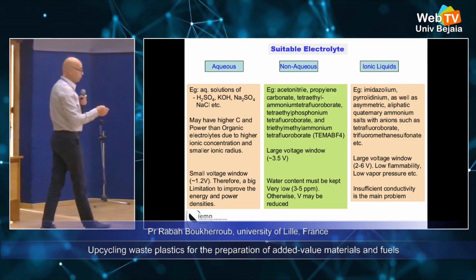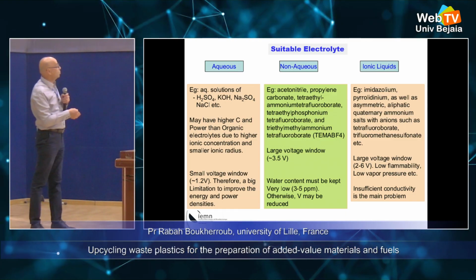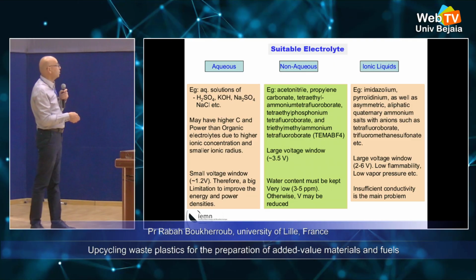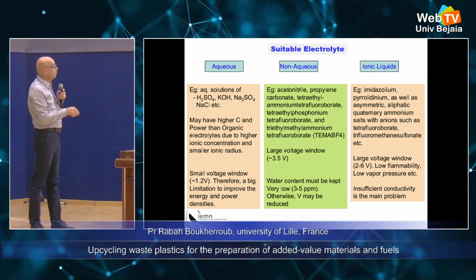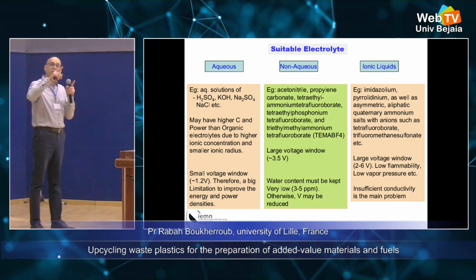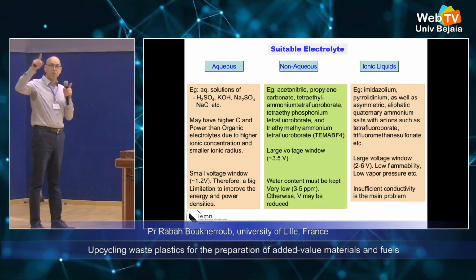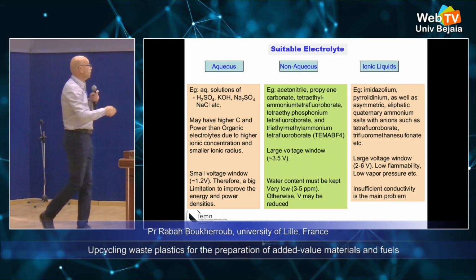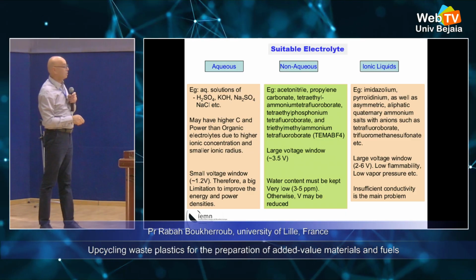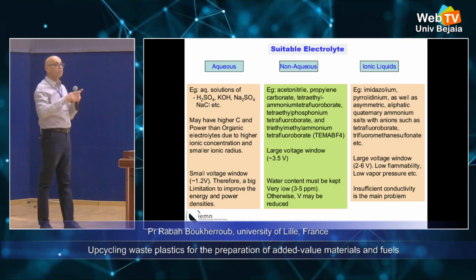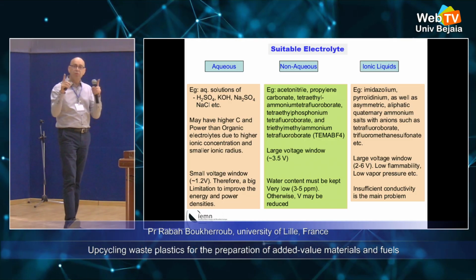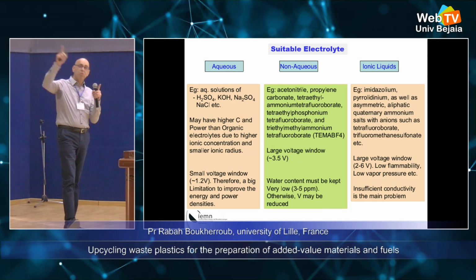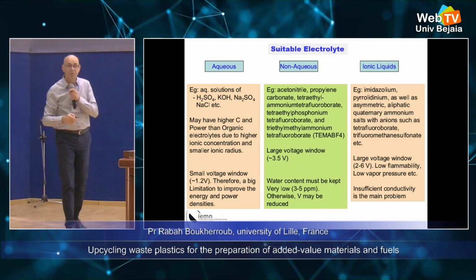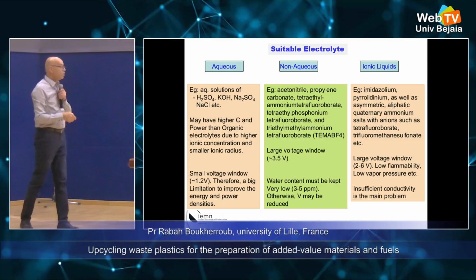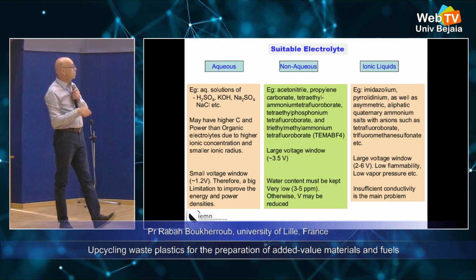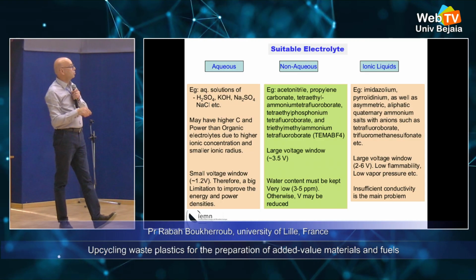Okay, so these are the different electrolytes you use. Aqueous, it's green, but the problem is you're limited by the small voltage. As I said, the energy you store is directly linear to the square of the applied voltage. So it's really quite small. And the reason, of course, is that when you use water, if you go a little bit too high, you have either oxygen evolution or hydrogen evolution, what we call water electrolysis. So this is really not the way you can reach a high energy using supercapacitors.